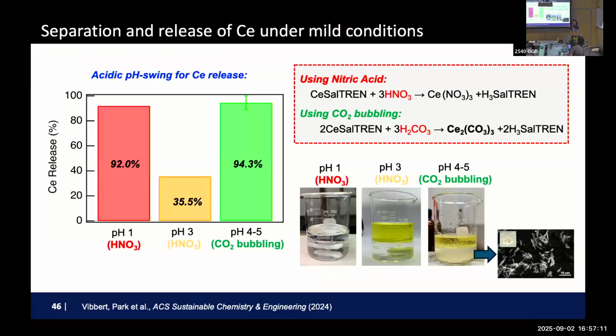And this isn't what's happening if my screen only showed me this figure. And I'm confused, right? It's like, why? It's weird. So then I finally went into the lab to see why this is happening. And then she showed me these 3 beakers. Now I know why. She didn't tell me this was cloudy, right? What happened was, when you bubble CO2, we were making cerium carbonate. So by doing the precipitation in the water phase, we keep pulling more metal out of the organic phase. So even at really mild pH conditions, we were able to recover all the cerium we wanted.